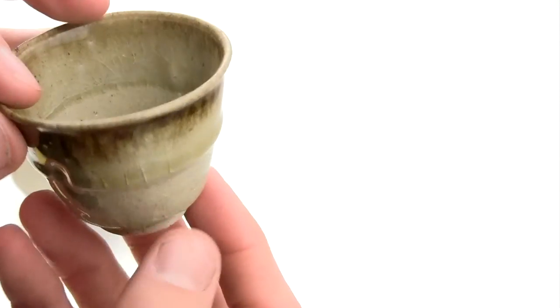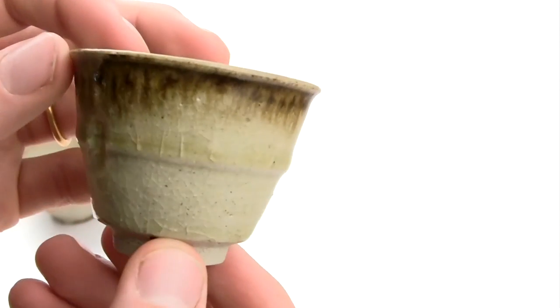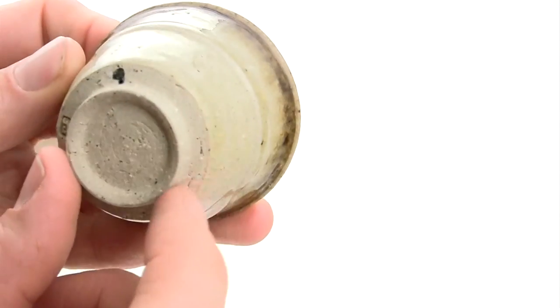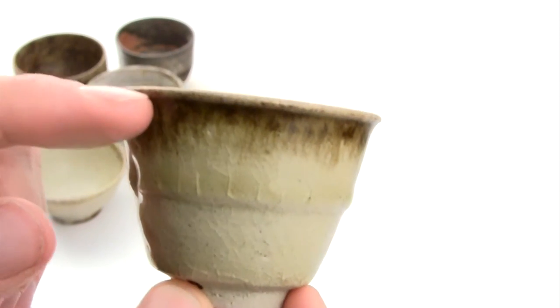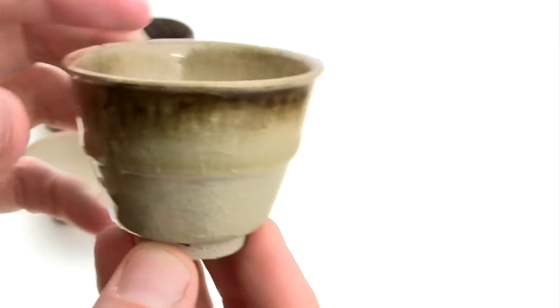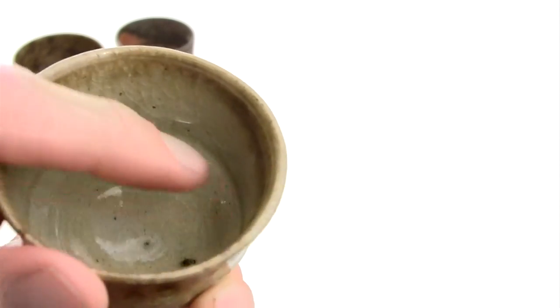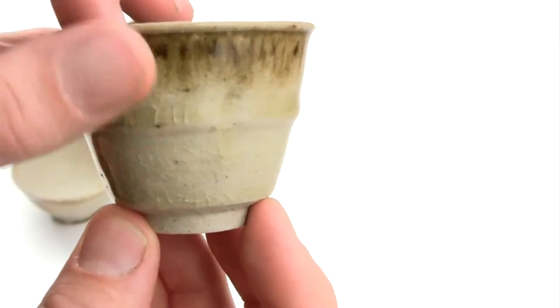I make pots or cups in every technique I can find. So this is a small cup fired in an electric kiln. It's a light stoneware clay with quite a lot of sand in it — you can see a large sand particle flowing out here. I've dipped this cup into an earthenware slip that's turned into a glaze at these temperatures, and then a clear glaze on top of that. This earthenware glaze will make the clear glaze flow quite a lot. So I've done these rims, indentations, and lines on the inside to collect that and pool it, making a decorative effect from the natural flowing of the glaze.